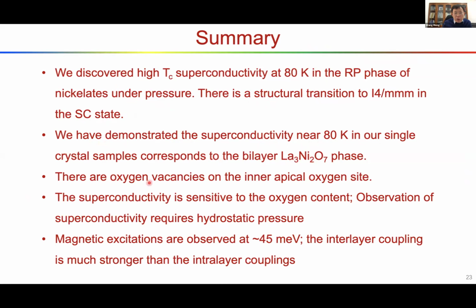And the oxygen vacancies are very serious in these materials, especially for the inner apical oxygen site. The superconductivity is sensitive to the oxygen content. If we want to observe superconductivity, it also requires very homogeneous hydrostatic pressure. That's very important to study superconductivity under high pressure.